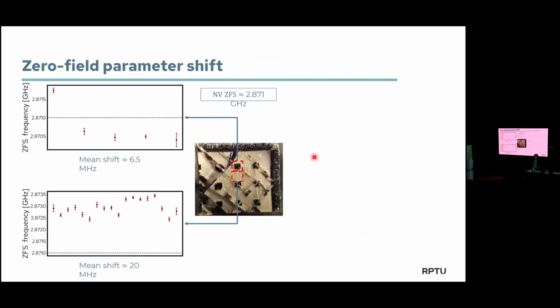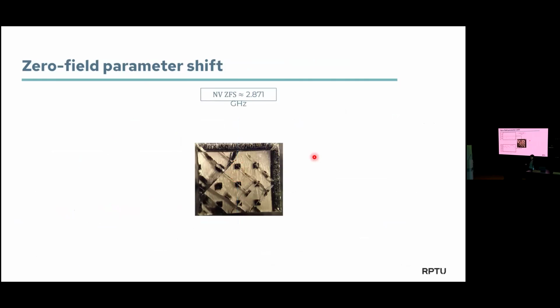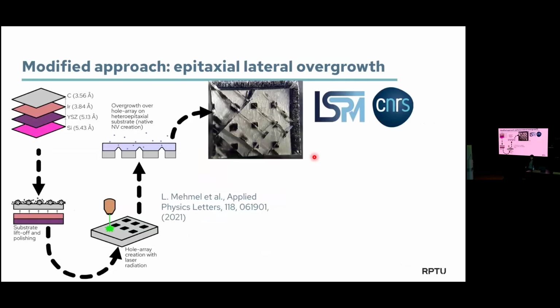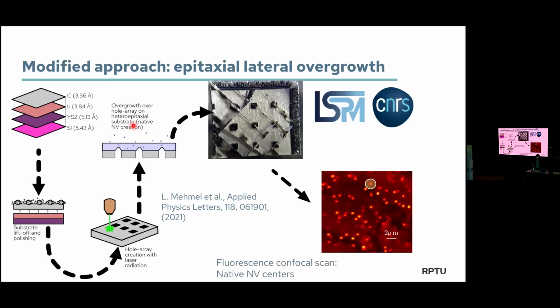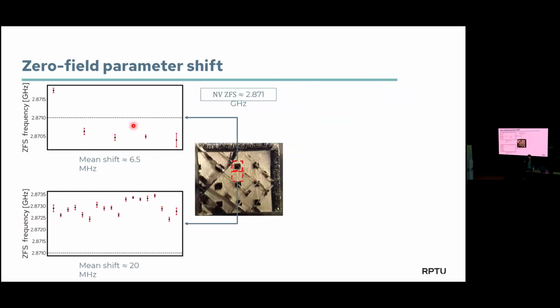It's a general problem, as far as I know, if you have the wrong type of reactor. No, typically not, but you have to keep in mind also here that the final growth is done when the silicon substrate is already removed. So in this bad material we might still have some silicon, but in the high purity layer on top, we don't see any silicon anymore. Exactly. So this is a bit the material side.